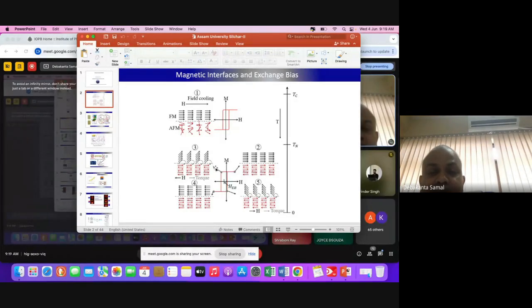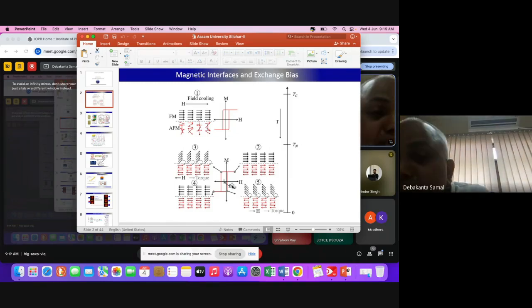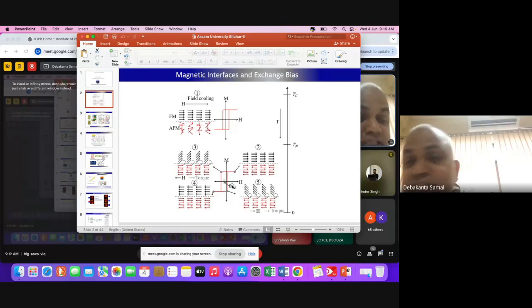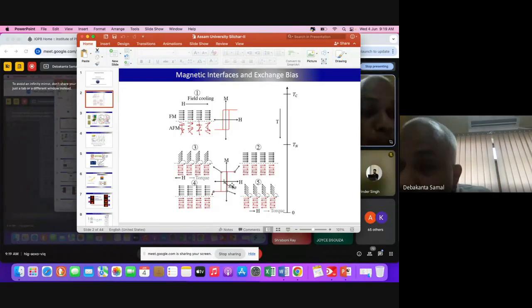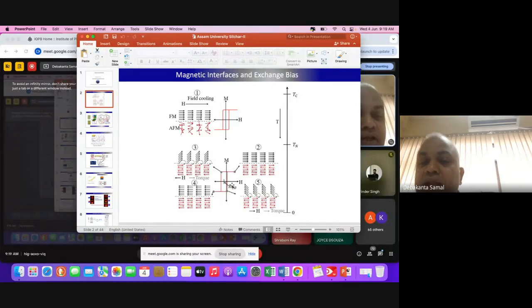Now you see the hysteresis has completely shifted. It is not a symmetric hysteresis. The coercivity on the negative side is more, and the coercivity on the positive side is less. So you see an asymmetry in the hysteresis. The hysteresis is not symmetric around H equal to 0. And this asymmetry is known as exchange bias.